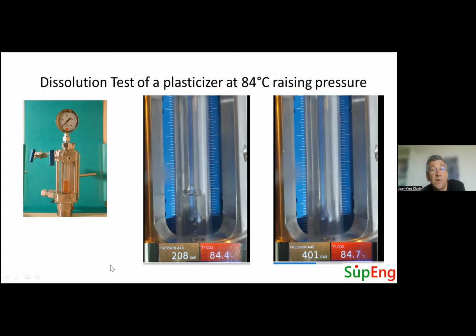And this is a very good example, this application of extraction of plasticizer from a plastic, as we have very, very good solubility, which is quite an exception, but we have to take this opportunity. Optimizing the thermodynamics, we can reach some domain here above 400 bar, where we have full solubility. We are actually in what could be called the supercritical state of the mixture, because whatever the amount of extract that we put in the cell, if we pressurize it to these conditions, we have only one phase. So we can say that we don't have any thermodynamic limitation. We don't have any solubility limitation for this extraction. So this is a very nice extraction, and there is, from my point of view, a great potential for this recycling of plastic.